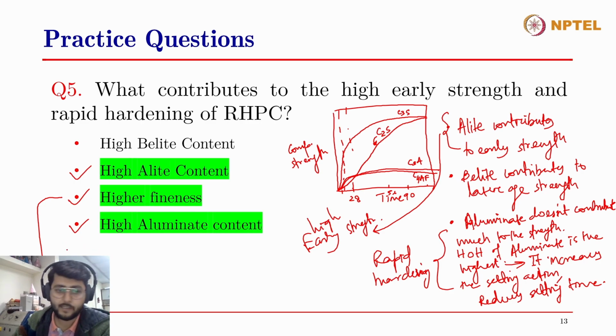So typically, when a cement is finer, it will have a large surface area. These large surfaces will act as sites for the hydration products to get deposited on them, and the dissolution action will also be accelerated when the surface area is higher. So higher fineness of cement increases the rate of dissolution of clinker phases.